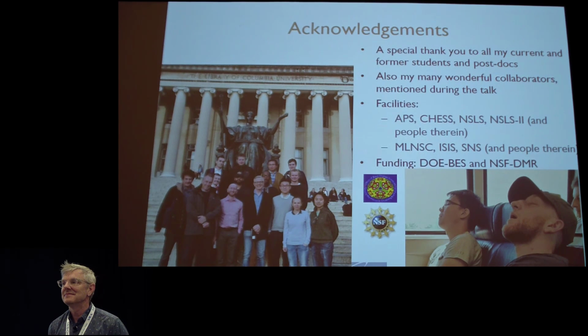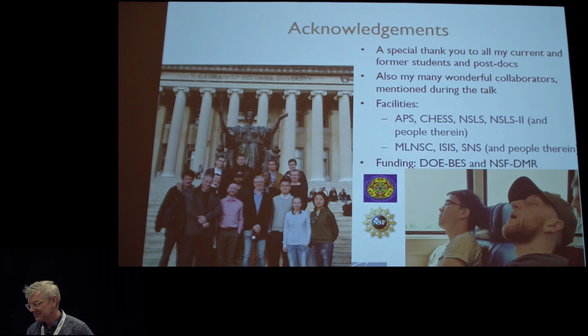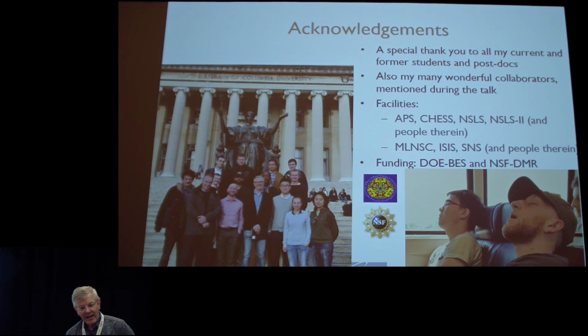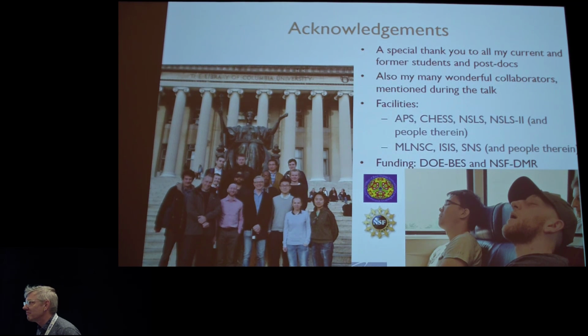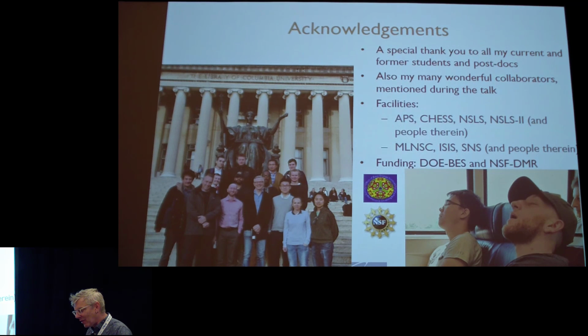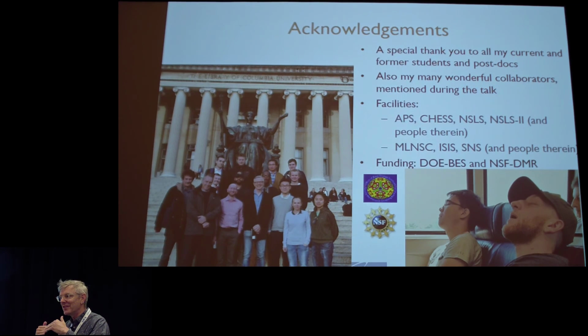So that's quite a body of work. It's really absolutely terrific. It was a terrific talk. One of the things that surprised me most about it was this ability to measure things in organics at such a small weight percent so reliably, apparently. Can you say a few more words about that? How do you extract that from the general solvent signal? Yeah, it's basically a signal to noise issue. We were always feeling that we couldn't do it because you count for longer, you get more counts, but you're getting more counts from the solvent as well as from the signal. So you just simply have to hit it with enough photons that, even with this very large background signal, you get your signal to noise in the right place.